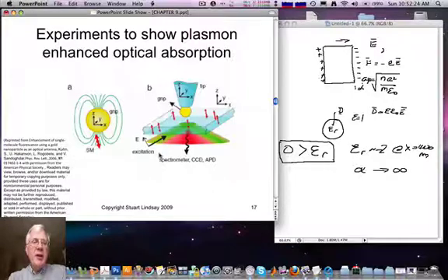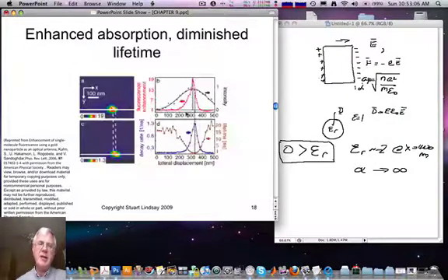This experiment shown here addressed that question by using an atomic force microscope probe to hold a gold nanoparticle over a glass surface to which were bound fairly sparsely single fluorescent molecules, which were then excited with a laser field imposed through an objective lens shown down here. Because of the use of an AFM to hold the gold particle in place, this height could be adjusted to see if there was a magic distance at which the electric field enhancement exceeded the effects of quenching in the metal. The answer, at least in this experiment, apparently is yes.